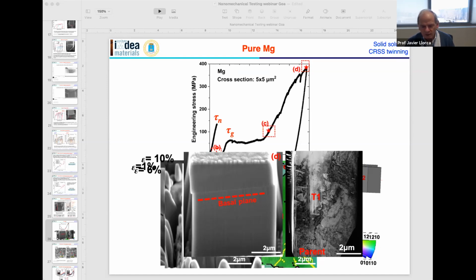But when you go to a different g vector, you can see that you have a dislocations here. So basically what you can see is that in the twin, you have c+a pyramidal slip, while in the parent, what you get is basically basal slip. So that means that you get a lot of information. And then these are the typical results.